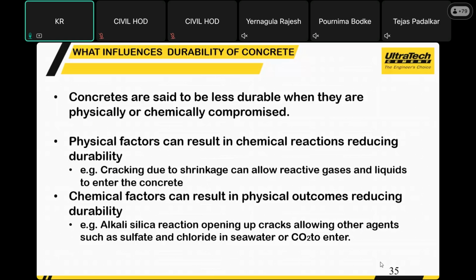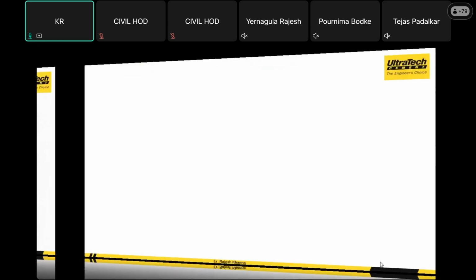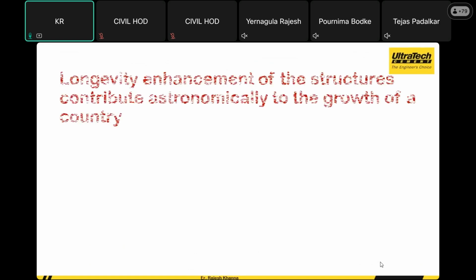So that is how there are even certain challenges like alkali silica reaction, opening up cracks and allowing other agents to enter into the concrete and form the chloride or sulfide, forming on the steel bars and try to get into the corrosion rate in a higher way. So that's how this will influence the durability aspects in a big way.